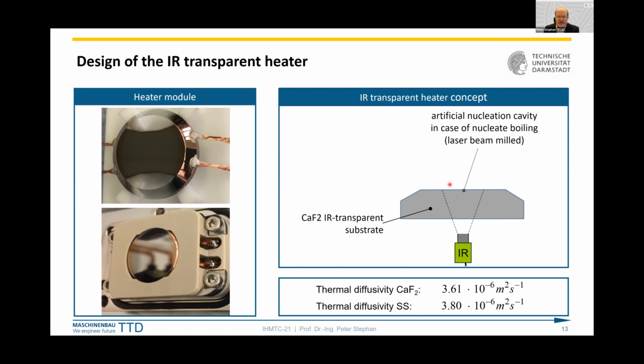Then we cover this infrared transparent glass with a chromium nitride layer of only a little less than half a micrometer, 400 nanometers, and this has basically an emissivity of 1. So when we observe with the infrared camera, fully calibrated, pixel-wise, in situ calibrated, we observe a temperature profile.